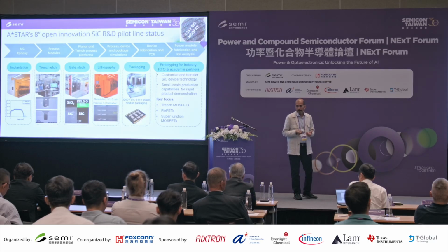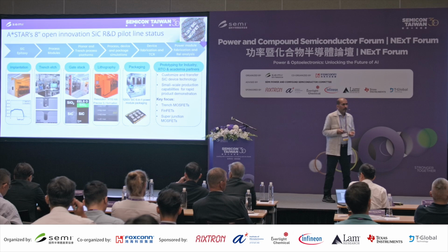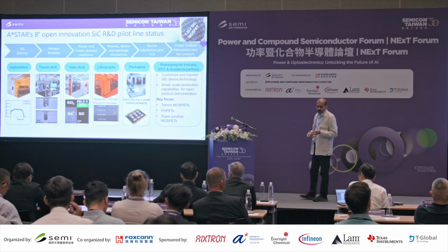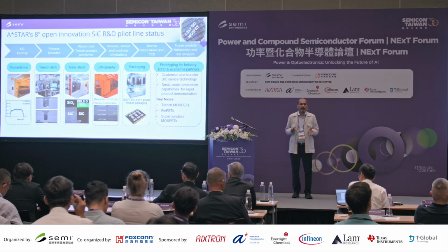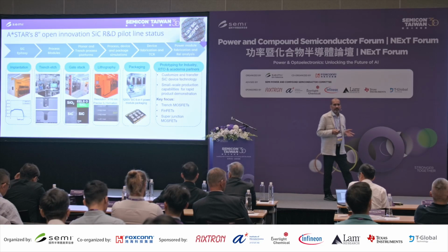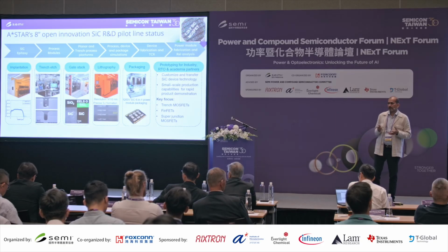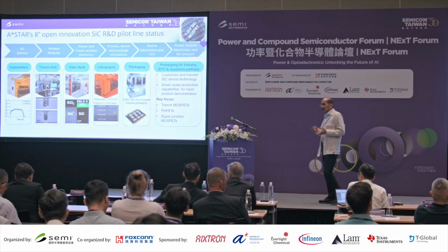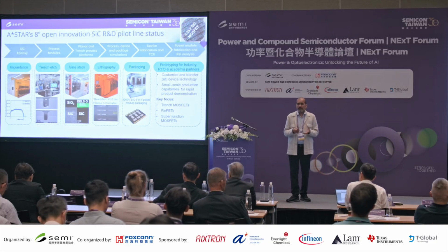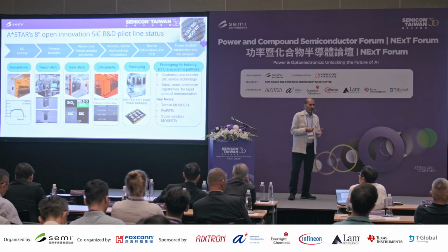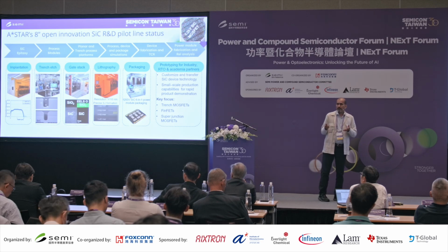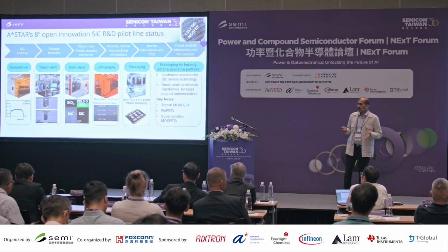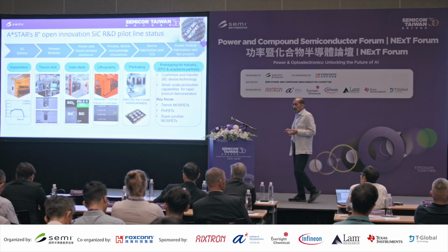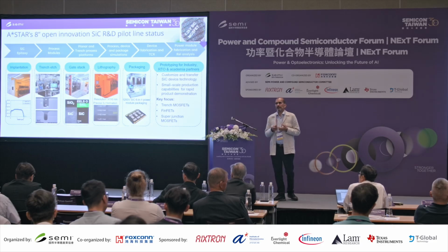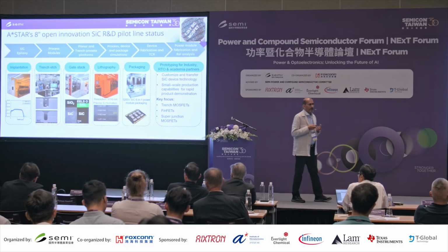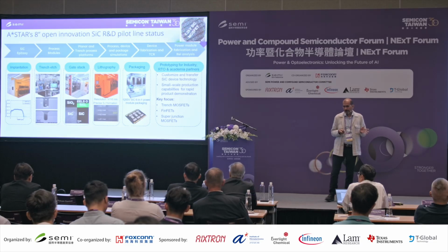Let me talk about the status. This is the status of our line. Besides epitaxy, we have implantation, where our core is to apply channeling implant. The silicon industry was running away from channeling, finding solutions such as tilted implants at 4 degrees, 7 degrees, different angles to avoid channeling. Silicon carbide in the past never utilized channeling, but recently you can see a lot of publications on channeling, and we have implemented channeling in our line. For implementation of the channeling, we have collaborated with Nissin, who has an integrated XRD so that we can put the ions correctly inside the right channels.